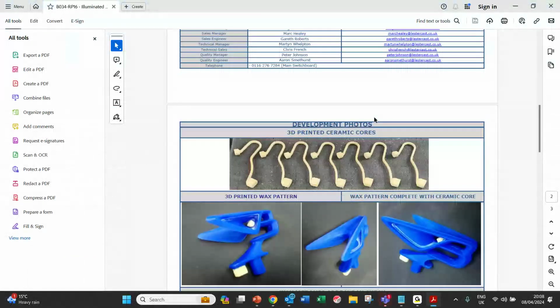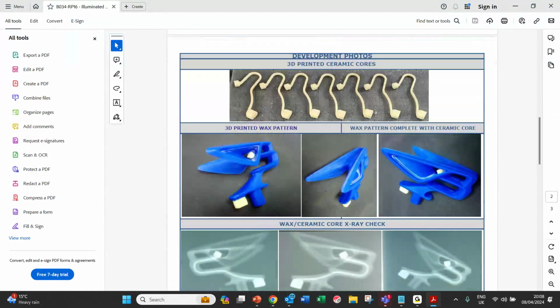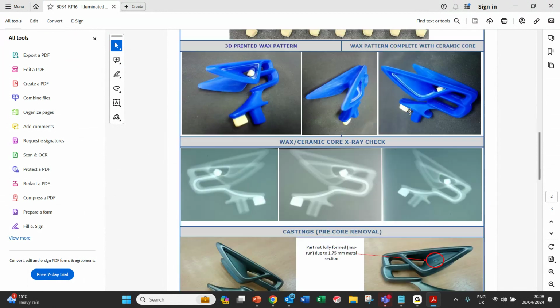A few images are on here. So those were the 3D printed cores, and the patterns were printed in two halves and the ceramic laid inside and then sealed. So we've got a full sealed resin pattern. Of course, we needed to do some X-ray on those patterns to make sure at this stage we had no breakage. We didn't know what was going to happen with that core once we started putting stainless steel in the mold, whether it was actually going to break and fracture.